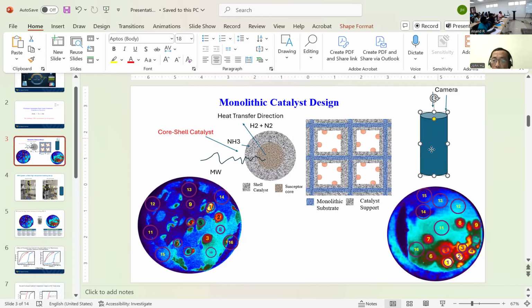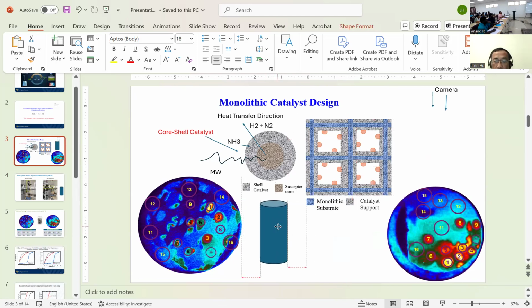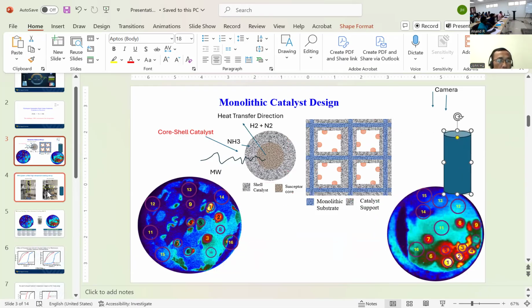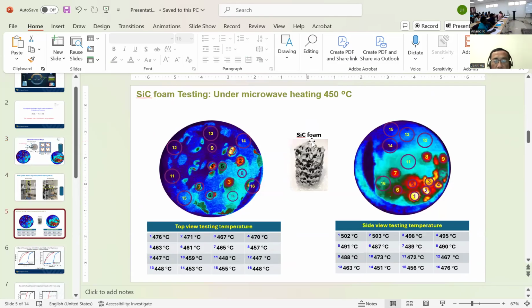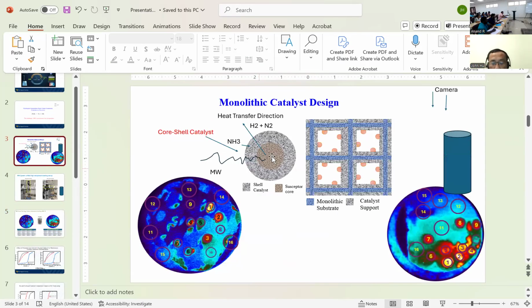To illustrate, you can print a perfect 3D printed catalyst cylinder shape. But unfortunately, in the picture here, I show you the one we cut using a machine, because for silicon carbide we couldn't find a good ink, but alumina silica you can print perfectly. For silicon carbide, we have to take a foam and machine it, because silicon carbide is microwave sensitive. We want to put it in the core and coat it on a shell. So it is a different reaction mechanism.